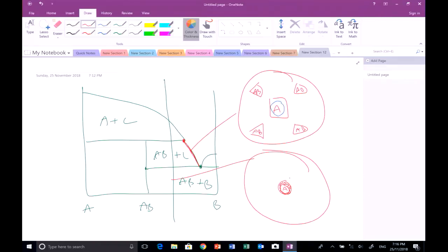And so you end up with what's called coring. You have a discrete grain you can see in the middle, and then there's a hard to visualize region around it where it was resorbing, and then the matrix outside of it, which is eutectic, and the secondary phase. Coring.